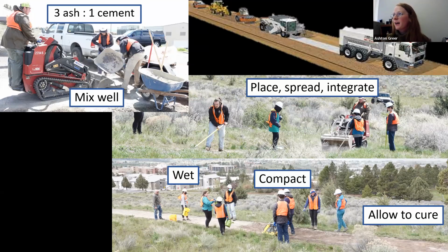Behind that, we had a team of students spreading the mix and integrating it with the existing trail surface. And they were followed up by groups who wet the surface and then compacted it with a plate compactor. So in this manner, we were able to resurface our 0.2-mile section over the course of about 7 hours on a Saturday. Overall, we used about 4 cubic yards of ash, 1.3 cubic yards of cement, and about 1 cubic yard of water.